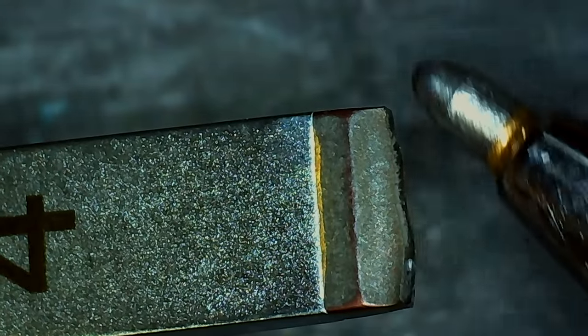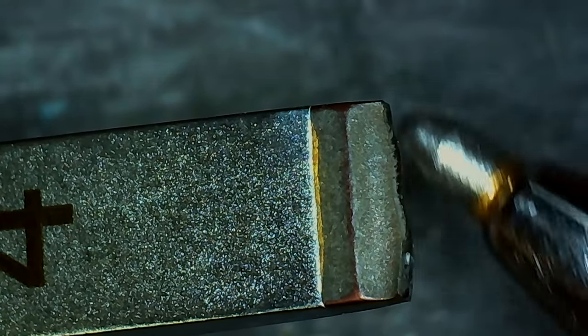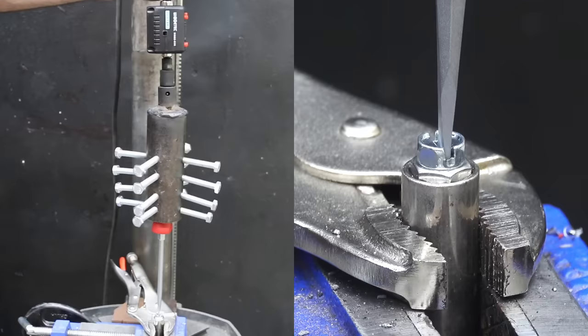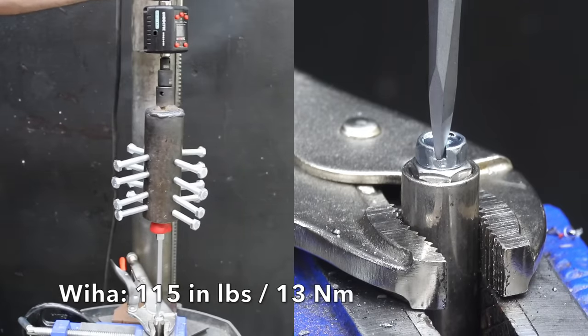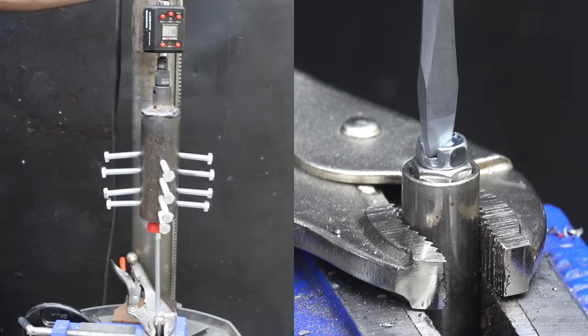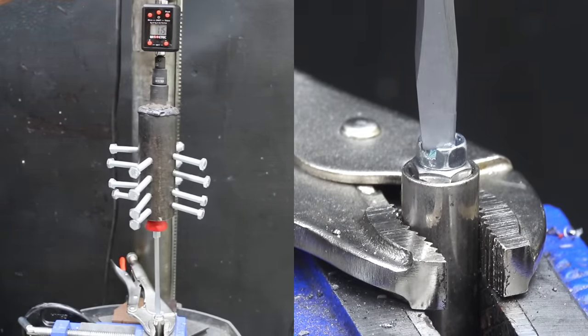Considering the thickness of the blade, the Swiss Tools actually did fairly well, but it finally broke at 89 inch pounds. And the Wiha brand, which claims to be extra heavy duty, performed very well at 115 inch pounds and moves into second place behind the Wera brand. The screwdriver did experience a small bend.